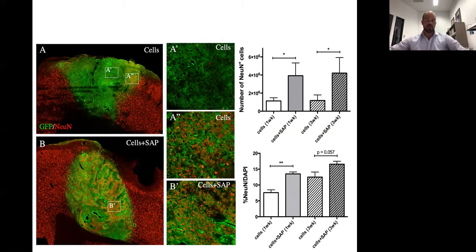And so we stained for a whole bunch of different cell types, but I just wanted to show you why that's occurring by looking at this NeuN stain. So that's a stain for neurons. And what you can see is when we have the cell alone graft, these are very big grafts, we get a very heterogeneous distribution of neurons within that graft. So at the edges here, because you've got these neurons in the endogenous tissue, they're secreting a whole bunch of growth factors, and as you get diffusion of those growth factors into the graft, that's promoting differentiation. You can see that here. But as we go into the center of the graft, where you're not getting those biomolecules diffusing, you can see there's basically no neurons at all. But when we have that IKVAV epitope present, again inspired by laminin, you can see we're getting a very homogeneous distribution of these neurons throughout the graft, which is again accounting for what we're seeing in the behavioral recovery.